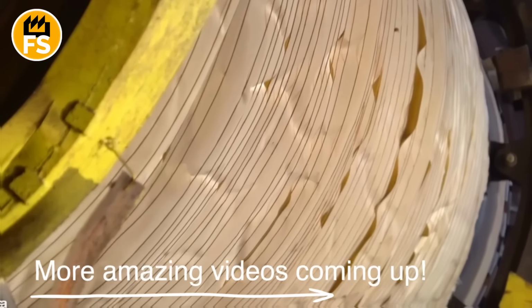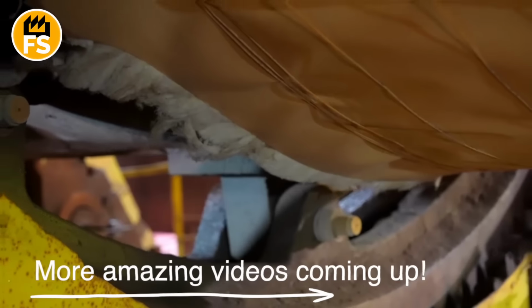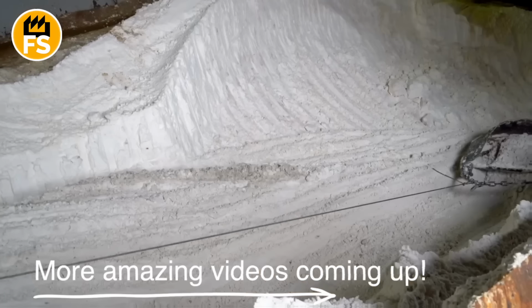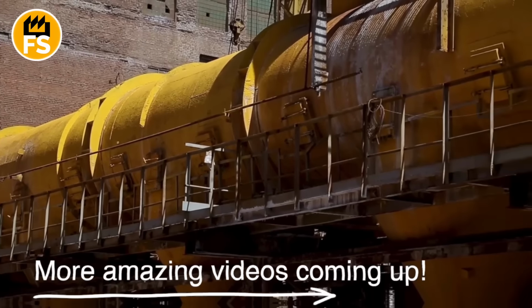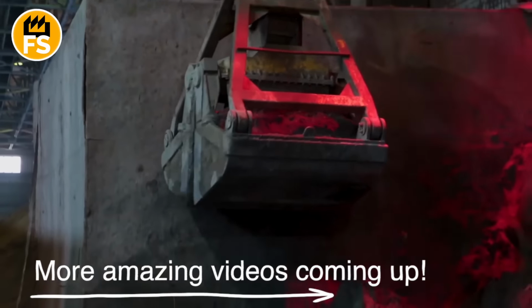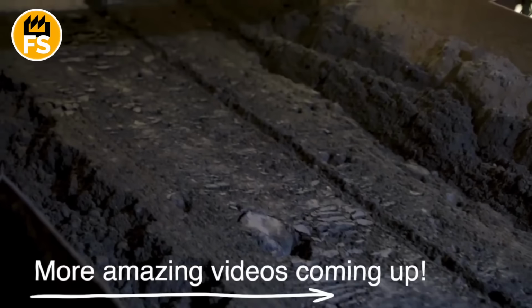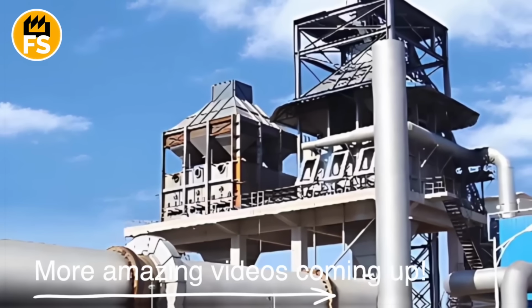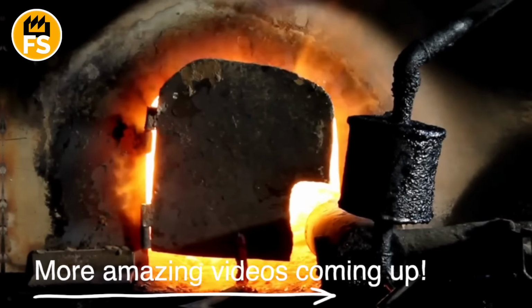Inside, temperatures exceed 1,380 degrees Fahrenheit, and the material gradually transforms into magnesium oxide. From the outside, it looks like an endless white ribbon of powder, being fed by conveyor into the scorching chambers and emerging with a completely different structure. The final stage is electrolysis. The oxide enters sealed high-temperature chambers where it's mixed with salt flux. This happens either in smelting vats or in special crucibles, where the material gradually transforms into a thick, molten mass.